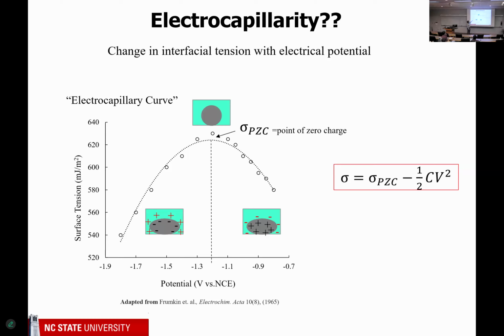But I'd like to point out to you that the change in tension shown here goes from 600 to 500. That's actually a big change. That's bigger than the entire surface tension of water. But still, at its minimum value, it's still 500, which is huge. That's bigger than mercury. So it will still form a droplet and not spread. You'll also notice, well, look at this equation. Shouldn't I just be able to apply any voltage and just keep lowering the tension, going on and on? So why did these people stop taking data? Here, why not apply a bigger voltage?